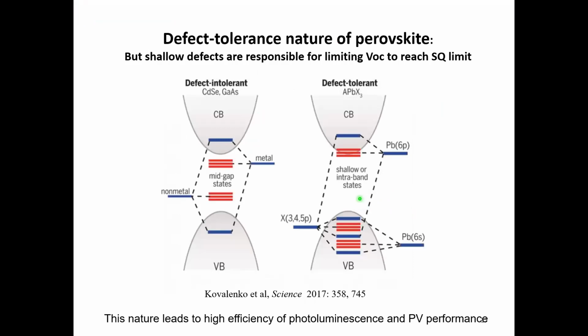Fortunately, perovskite has a very unique nature, so-called defect tolerance, having only very shallow traps. This leads to high efficiency of photoluminescence and PV performance. These very shallow traps enable suppressed recombination of light-excited carriers. So this is enabling very, very high output voltage from the solar cell.